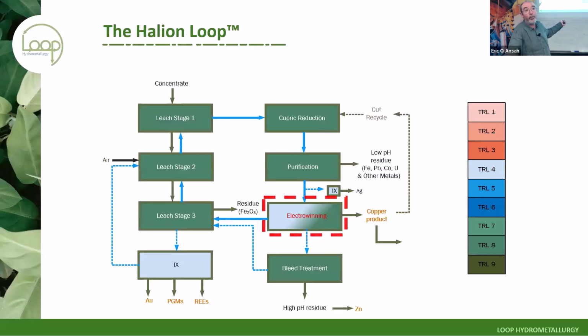By this stage, the mineral processing down the process is mostly depleted, and so you are putting the highest anodic energy, the highest redox potential against the most depleted mineral, where you extract the last vestiges of the base metals, you extract the lead, the gold, the PGMs, the rare earths, etc. And you take the overflow from the thickener and you IX it to recover those metals. It's a nice closed loop, and you can see why until you had this critical stage, you didn't have a closed loop, and that's why the existing previous technologies didn't get to market.